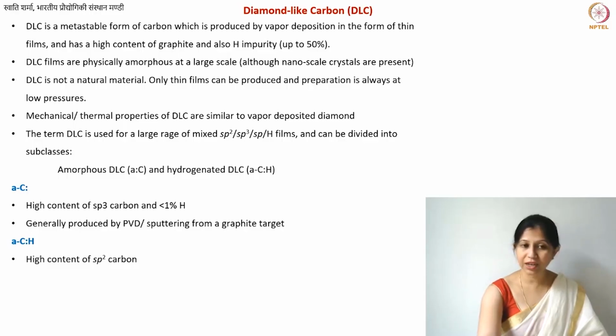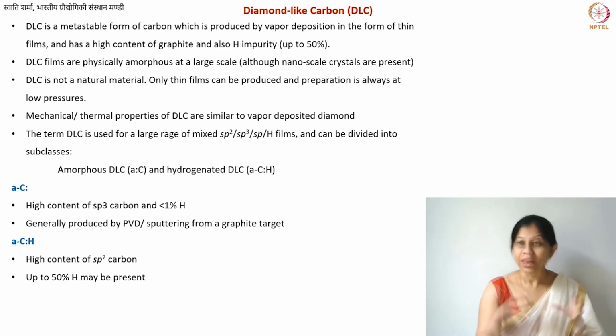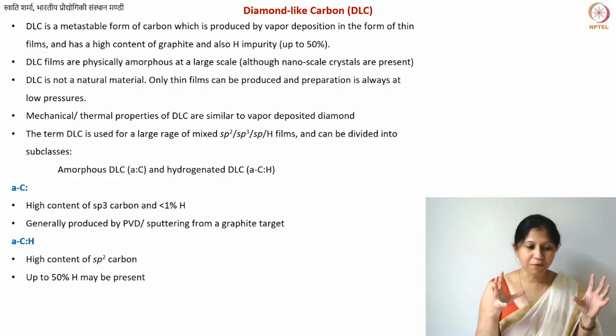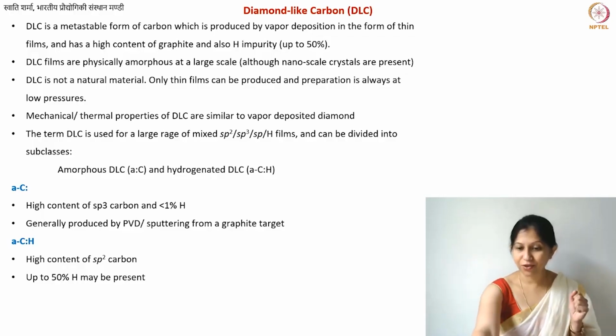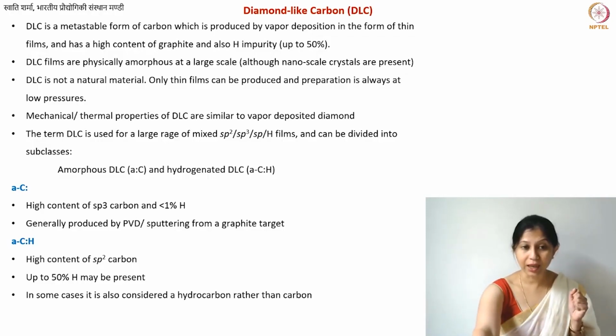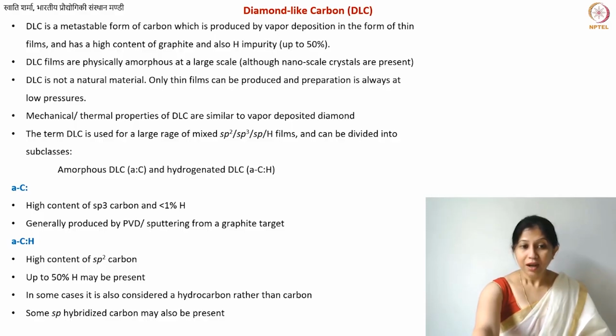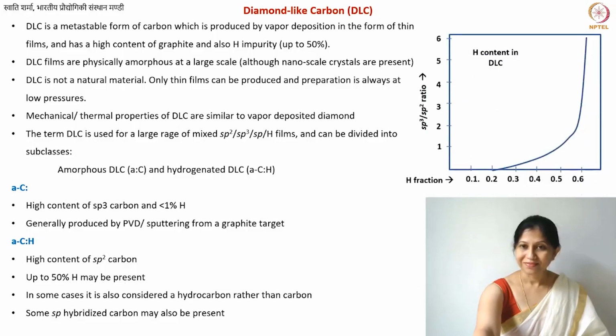In the case of hydrogenated DLC fabrication, what you have is a very high content, up to 50%, of sp2 type carbon and also up to 50% atomic fraction of hydrogen. So the point is that you can have a relatively much smaller fraction of sp3 type carbon. In fact, sometimes there is so much hydrogen in the material that people call it a hydrocarbon, rather than considering it a form of carbon. And some sp hybridized carbon, as I mentioned, can also be present.